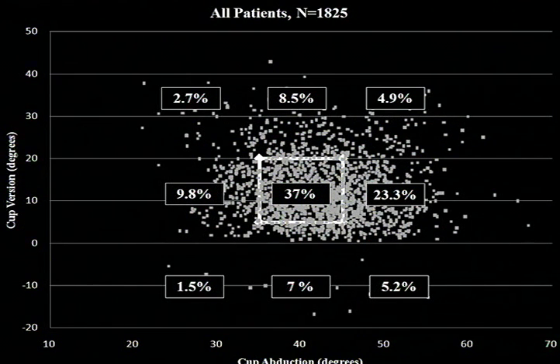This is another slide from a talk tomorrow. Each dot represents a cup position, and here is a pointer. Within this square, you need to put your acetabular cup. This is 5 to 15 to 20 degrees of anteversion. This is 35 to 45 or 30 to 45 degrees of lateral version. That's where you should have your cup.